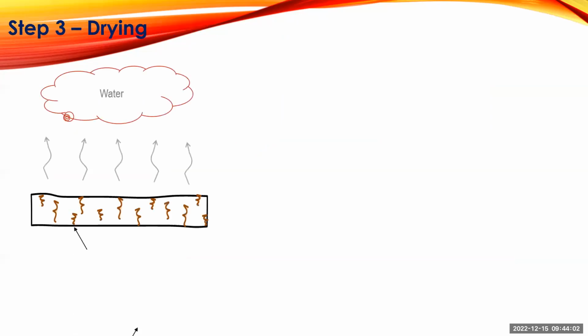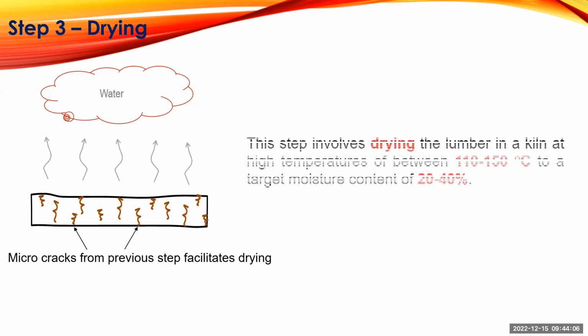After that, the compressed lumber will be subject to drying. This step involves drying the lumber in a kiln at a high temperature of between 110 to 150 until reaching a target moisture content between 20% to 40%. The drying is conducted without any drying defects such as split, crack, and warping.